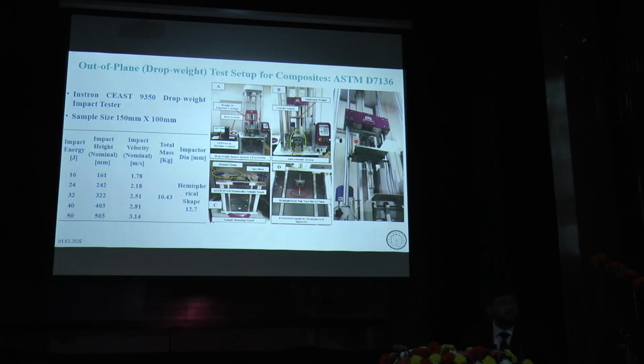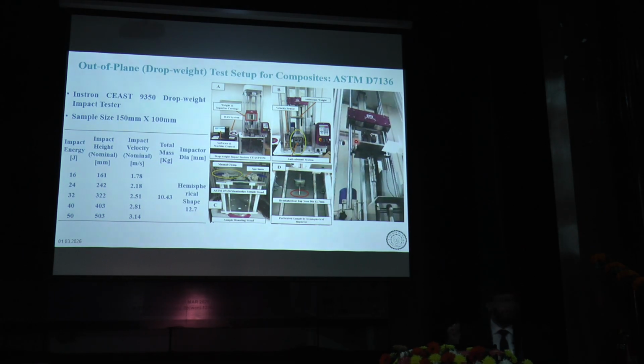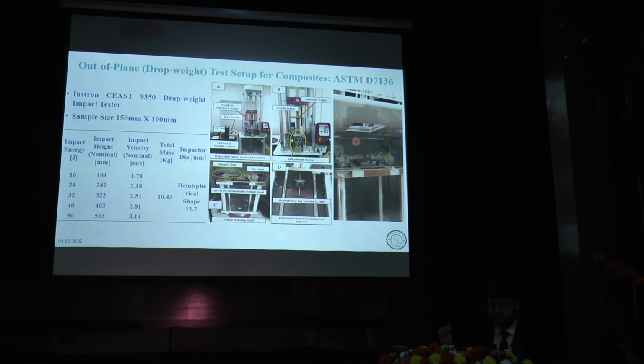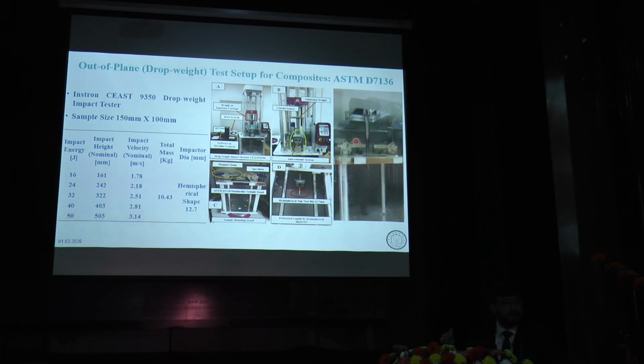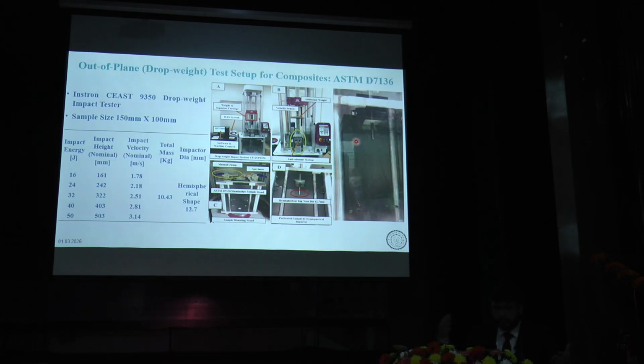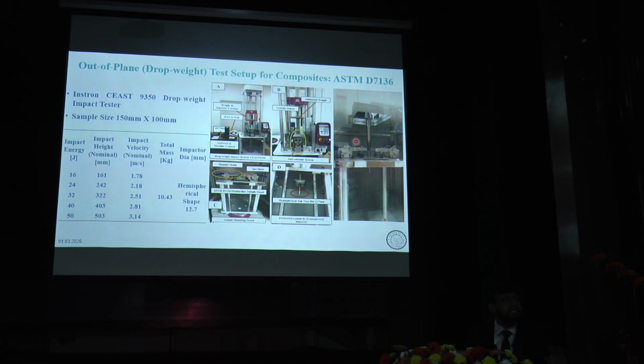In this case, we tried out-of-plane impact testing. We tested 5 different impacts from 5 different nominal heights and impact velocities, keeping the total weight of the drop weight exactly 10.45 kilograms with the same hemispherical shape of 12.7 mm. For example, at 50 joules, my structures were fully perforated. To choose this 16 to 50 joule segregation, I had to run a series of experiments - nearly 50 samples I had to waste - to understand the lower threshold, the intermediate threshold, and the perforation threshold.